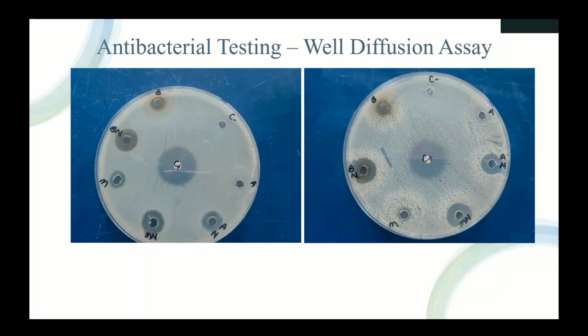But when we added the nanoparticles to the acacia honey, there was a significant inhibition of growth, about 50% that of the control. With the manuka honey nanoparticles and the buckwheat nanoparticles, although there was an increase in zone of inhibition, the increase was only about 30% above background. So right now, our hypothesis was disproven: manuka was not the best honey for the nanoparticle formation or antimicrobial activity. It was the acacia honey.